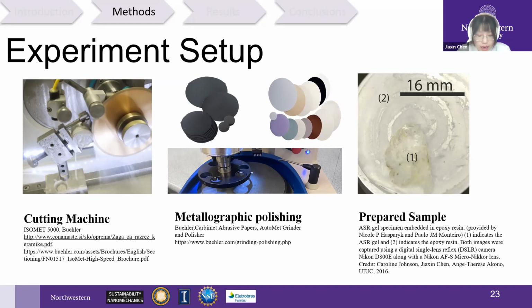After that, we used a diamond linear precision saw to cut our ASR gel crystals. We used oil-based cutting fluid to reduce the cutting heat. The reason we use oil-based fluid is because ASR gel crystals are sensitive to water exposure, as I said before. Second, we applied surface polishing using abrasive papers until the grit size was 1 micron to achieve a flat, smooth surface. Microscopic images between steps were used to check the surface roughness and also the surface microstructure.